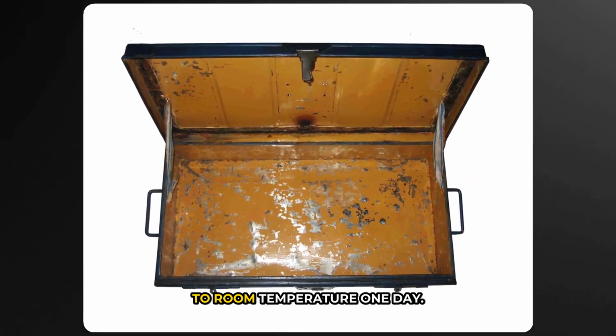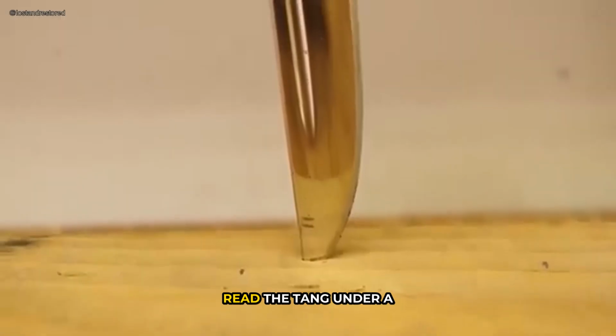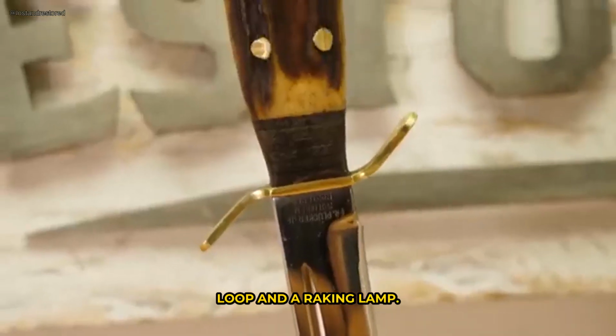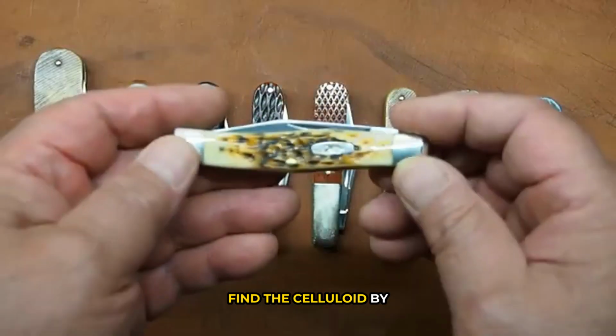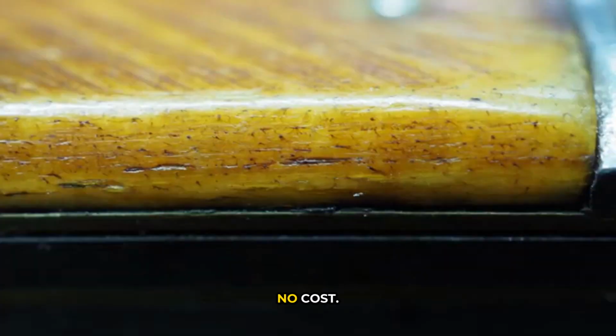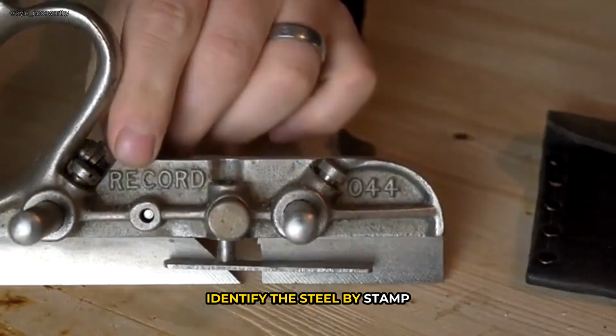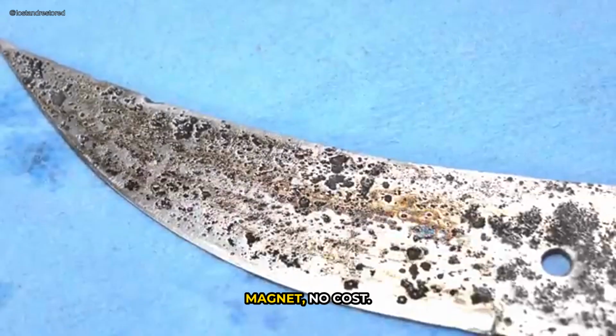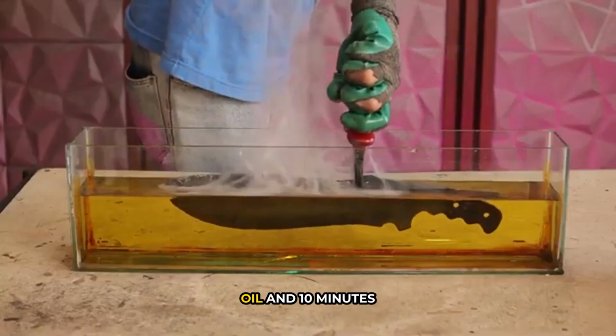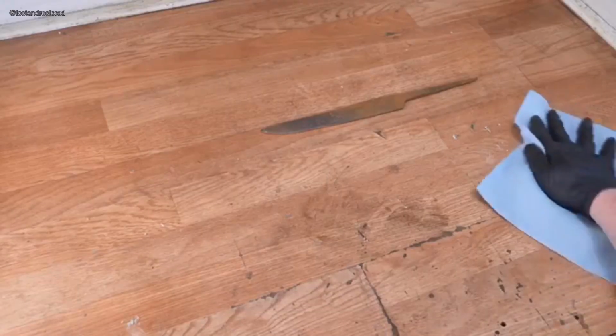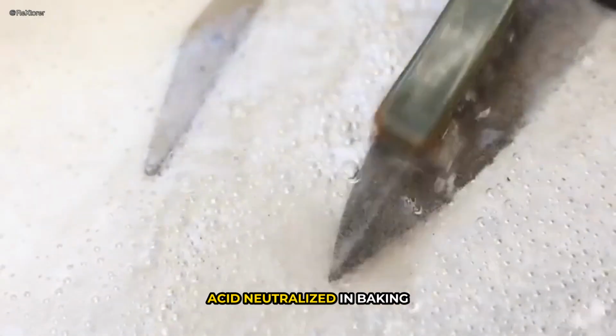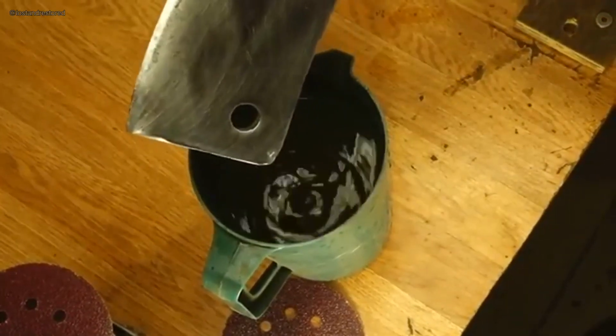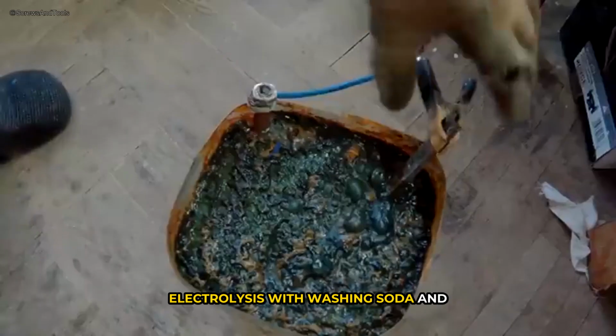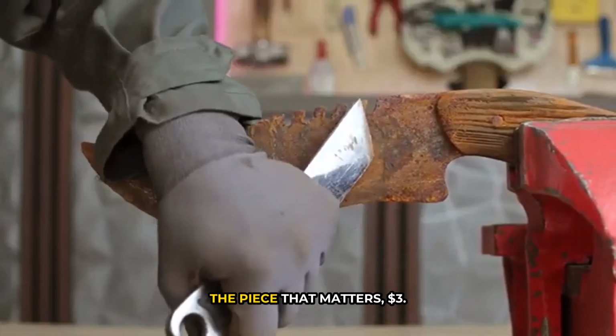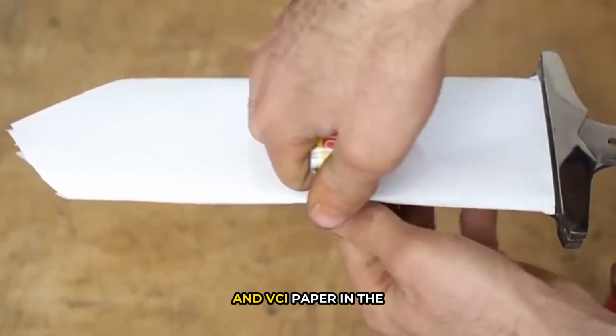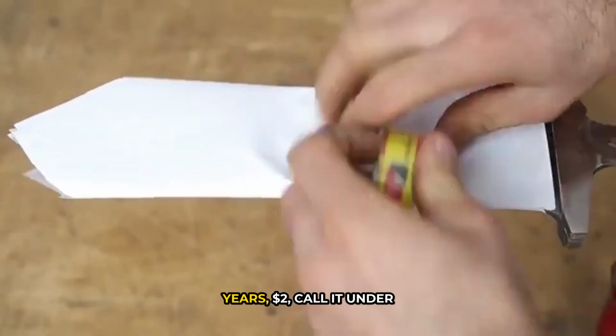Let the box come up to room temperature one day, no cost. Read the tang under a loupe and a raking lamp, $8. Find the celluloid by smell and get it out of there, no cost. Identify the steel by stamp and rust pattern, not by magnet, no cost. 3 days in mineral oil and 10 minutes with bronze wool, $10. 15 minutes in citric acid, neutralized in baking soda, under $2. Electrolysis with washing soda and a mild steel anode for the piece that matters, $3. And VCI paper in the drawer for the next 40 years, $2.